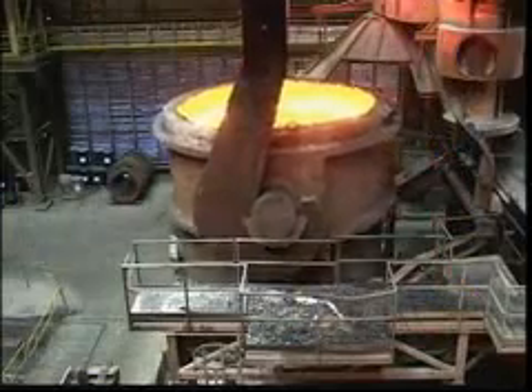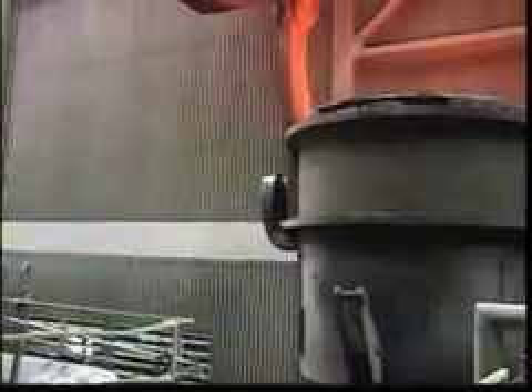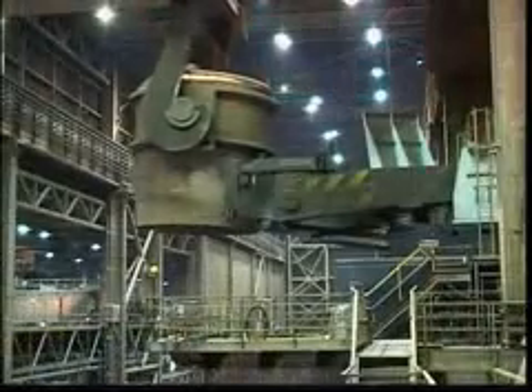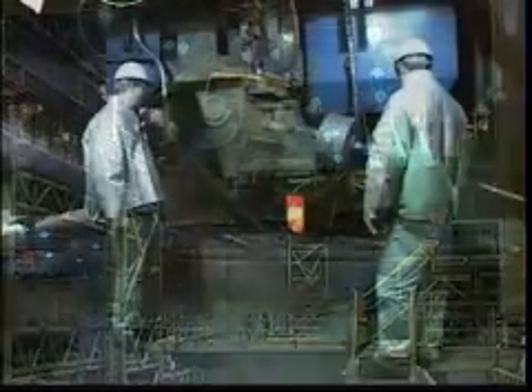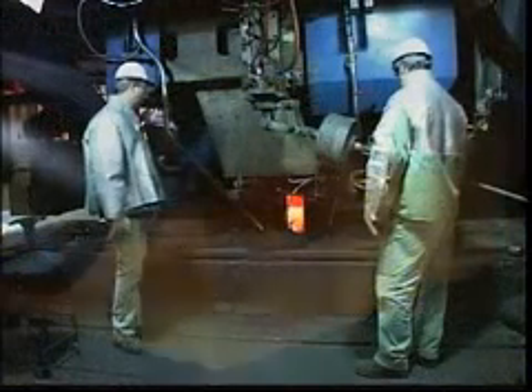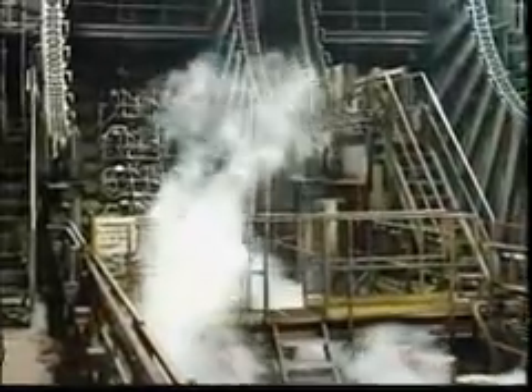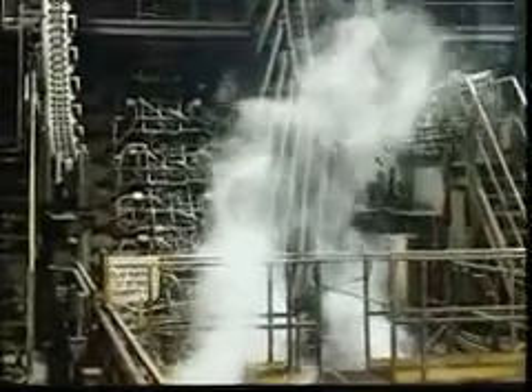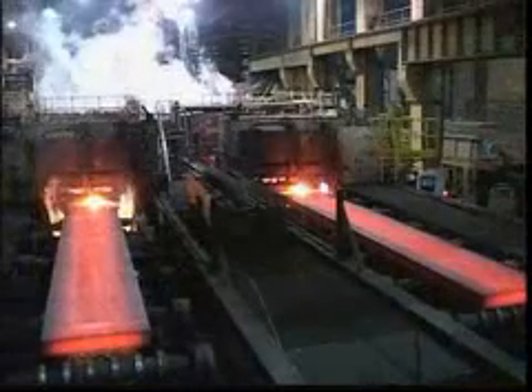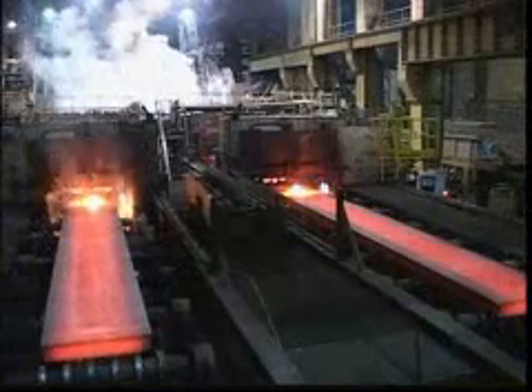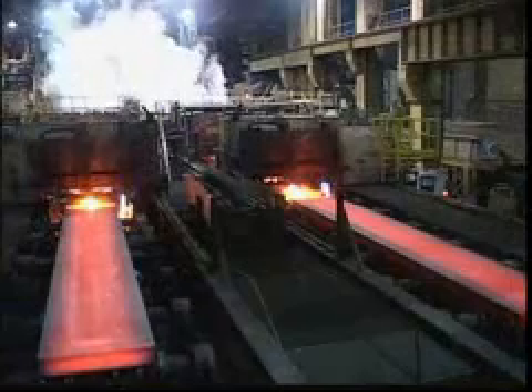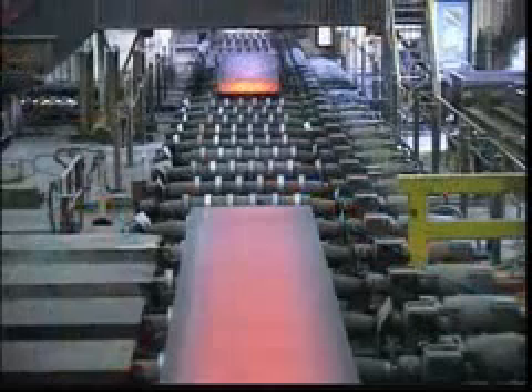Once the steel has been metallurgically refined, it is taken to our 2-strand caster, where the steel empties from a hole in the bottom of the ladle into the tundish, which allows the molten steel to enter 2 continuous molds. As the steel travels through the molds, water cools the advancing strands so they can solidify. As the 2 strands progress and form slabs, they are then torch cut into various lengths, depending on customer specifications.